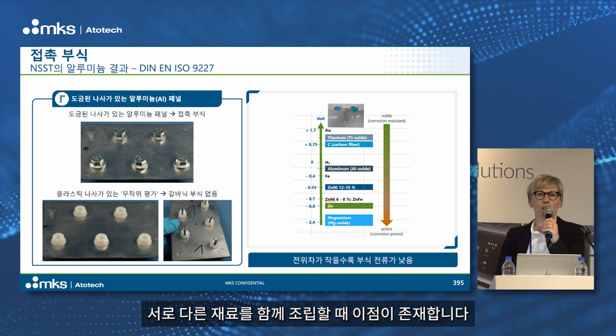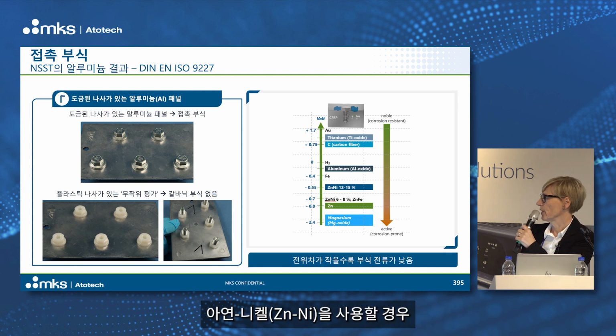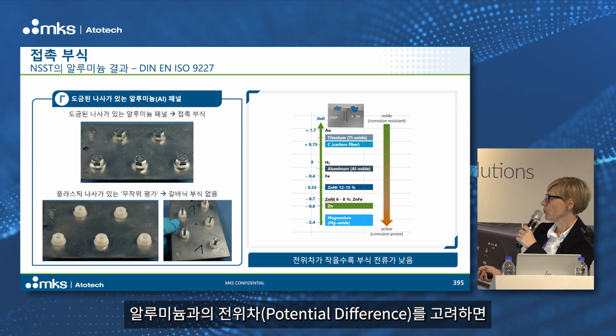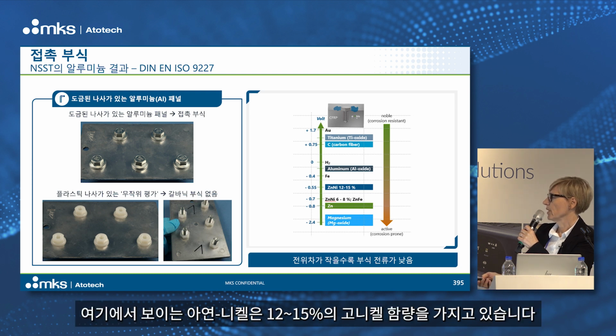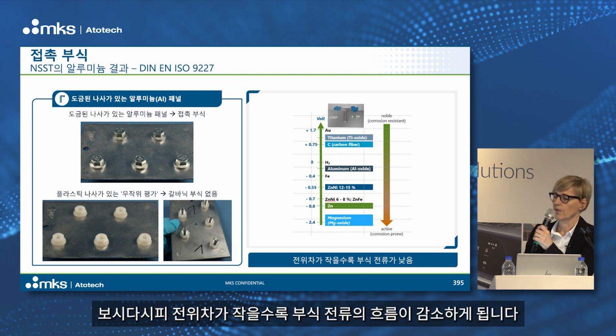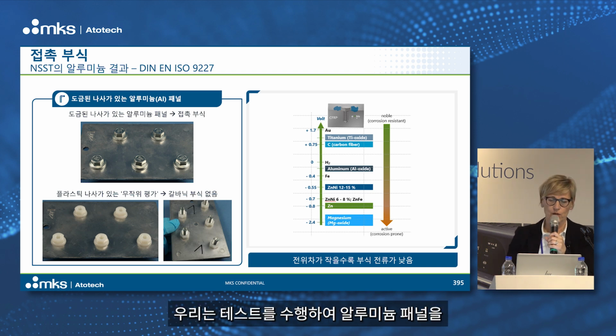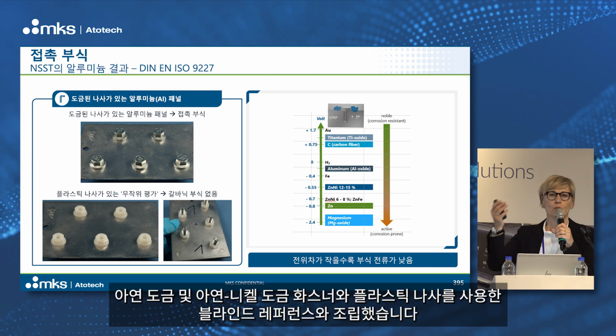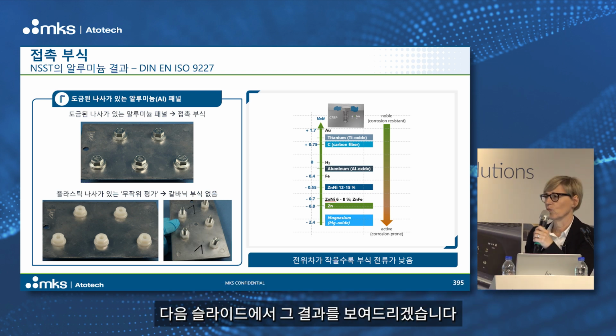Last but not least, we explained already today several times that there are advantages when we are mounting different materials together. If you are using zinc nickel, and you look at the potential difference from aluminium, you see zinc nickel with a high nickel incorporation, 12 to 15%, has the smallest difference, and the smaller the potential difference, the lower the flowing corrosion current. This is what you can see now. We did a test and mounted aluminium panels with zinc plated and zinc nickel plated fasteners, and just a blind reference with a plastic screw. We will see on the next slide what the outcome is.